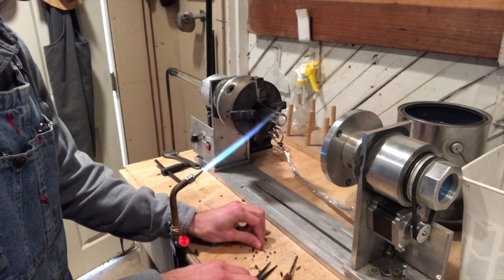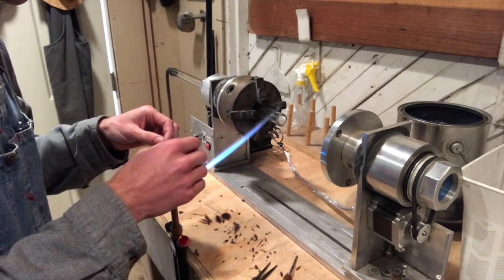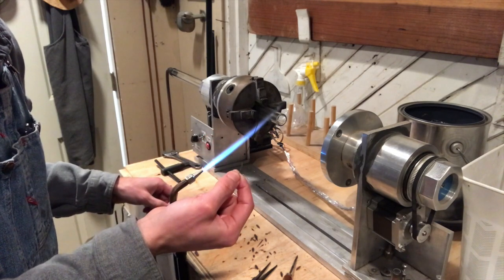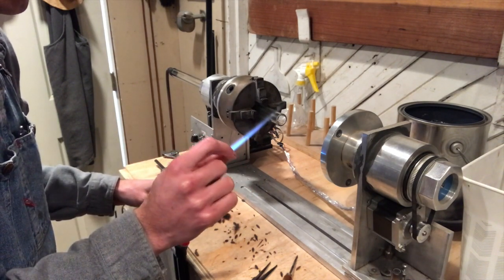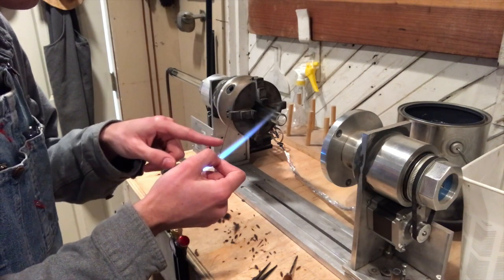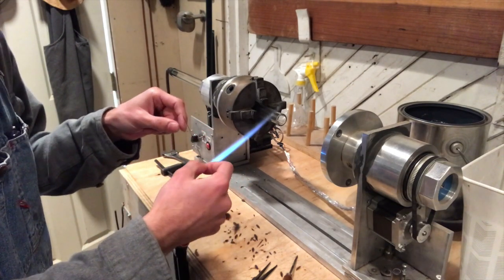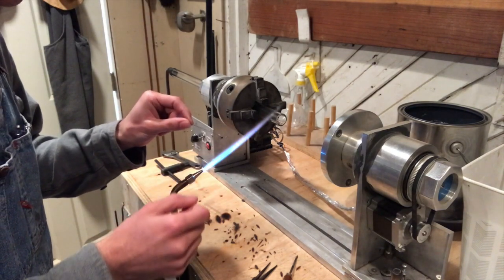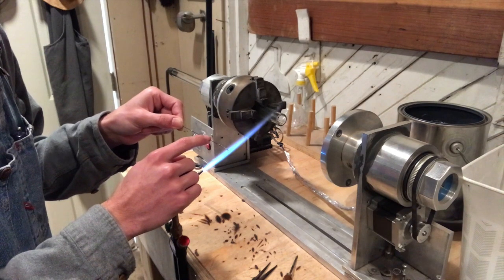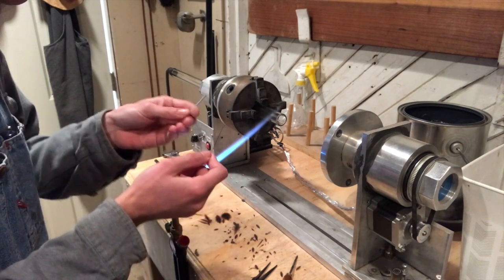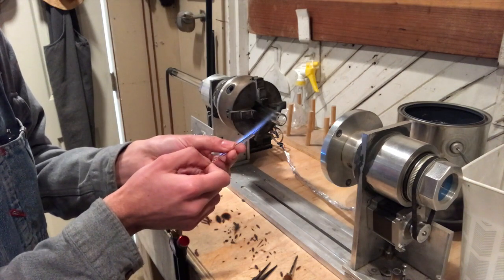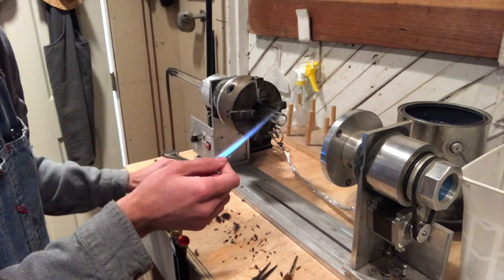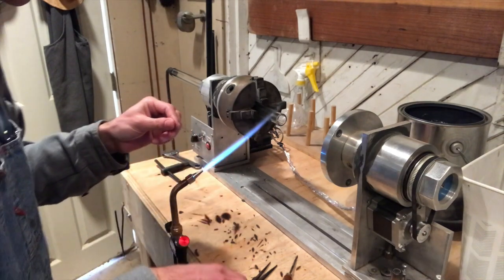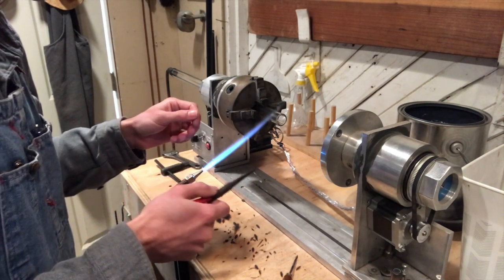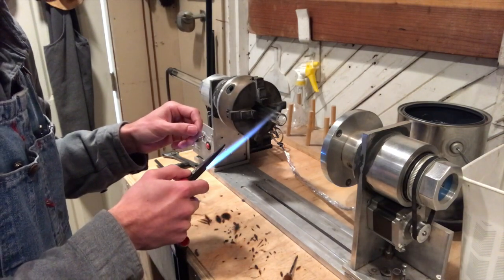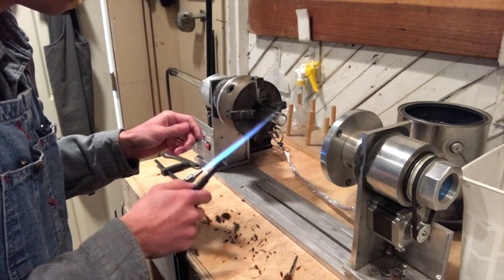To secure the filament to the lead-in glass stem, what we're going to have to do to the filament wire holding the nickel base electrode is heat up this tungsten wire in direct flame to a red hot, white hot temperature, because we want to build up an oxide layer on this tungsten wire so that when it adheres and seals to the glass stem, it ensures a nice tight vacuum seal. Otherwise, we're going to have irregularities on a very microscopic level, and that's not going to be beneficial in any way. So I'm going to now heat up the tungsten.